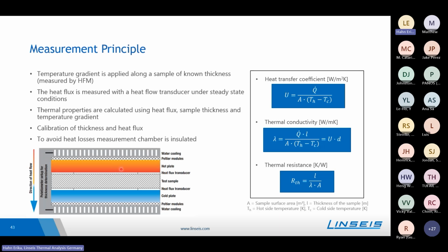So the system also uses the method of two plates. So here's the illustration of that. We have the hot plate and the cold plate, as well as the test sample in between. Between the sample and the plate, there's a heat flux transducer each, so above and below the sample, to determine then the heat flux through the sample. Out of the measurement, we can calculate the so-called heat transfer coefficient, also well known as the U value. This value is often used in the building industry or insulation material industry to be able to compare different materials. We can also calculate out of the heat flux and the sample geometry the thermal conductivity as well as the thermal resistance of the material.